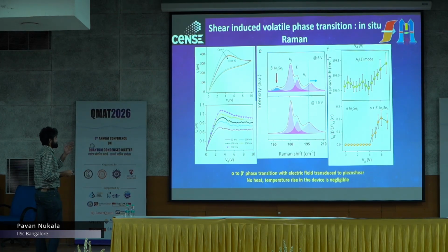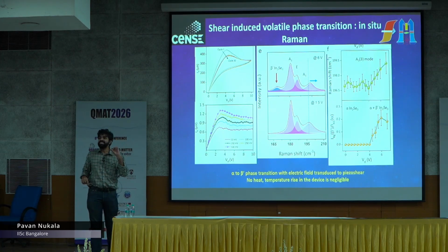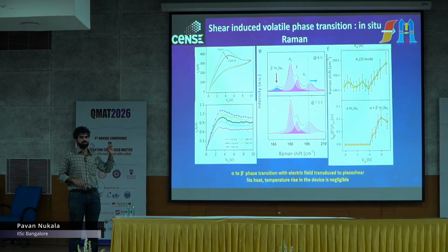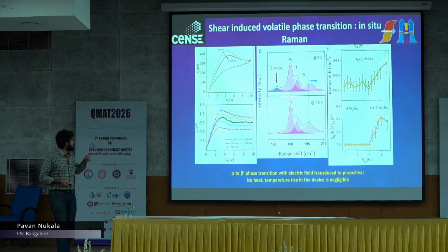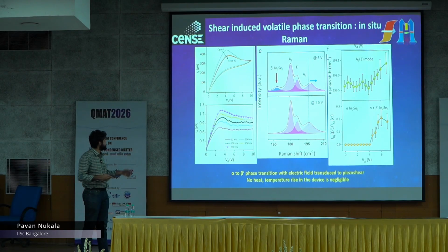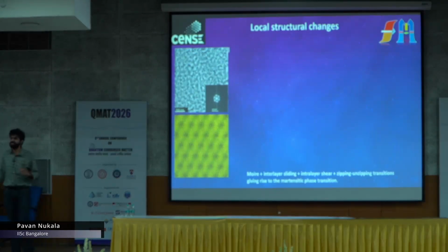So it's a high pressure phase and so on and so forth. Okay. So this is a phase transition, and it's a completely shear induced phase transition. If I look at the underlying temperature in this system, that's almost nothing, right? So we do have some simulations to look at the underlying temperature. That temperature rise is almost nothing.